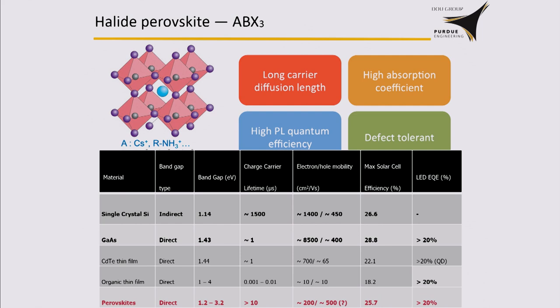So the efficiency of a perovskite solar cell is approaching 26% power conversion efficiency, almost the same as single crystalline silicon, much better than polycrystalline silicon. But this material is solution processable because of the ionic crystal lattice. It dissolves in organic solvent, so you can play with it just like playing with organic molecules. But at the same time, it crystallizes into perfect thin films and generates this great device performance.